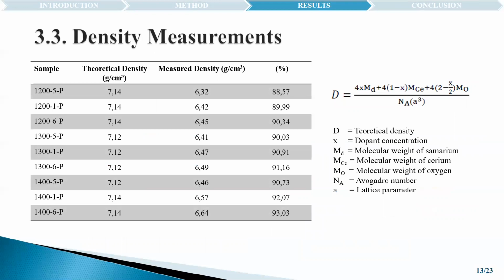Sample densities after sintering were determined using the Archimedes method. The theoretical density was calculated using lattice parameters. As expected, increasing sintering temperature and time caused an increase in the sample densities. It is possible to reach the density value obtained by performing 6 hours of sintering at 1200 degrees by 5 minutes at 1300 degrees. They are nearly the same values. At the same time, it was seen that increasing the sintering time from 1 hour to 6 hours had little effect on density values. Generally, in all sintering conditions, relative densities of more than 88% were achieved for the samples.